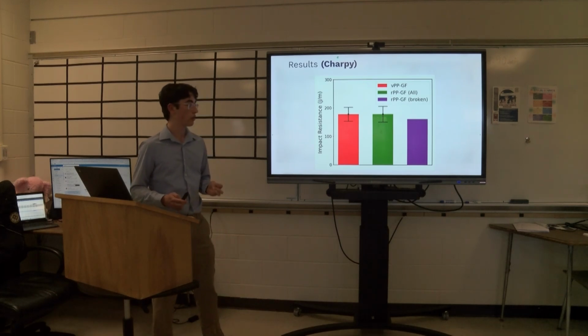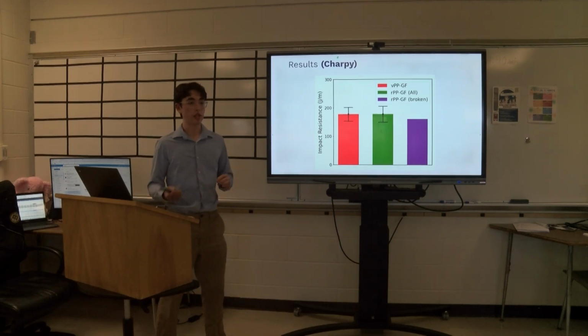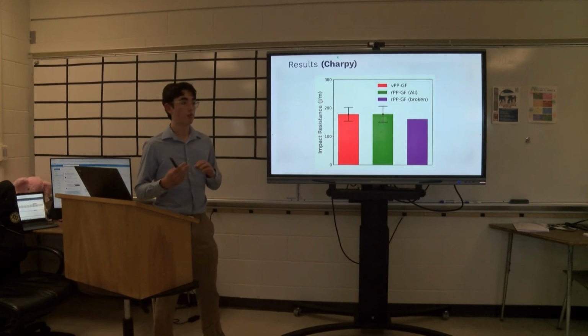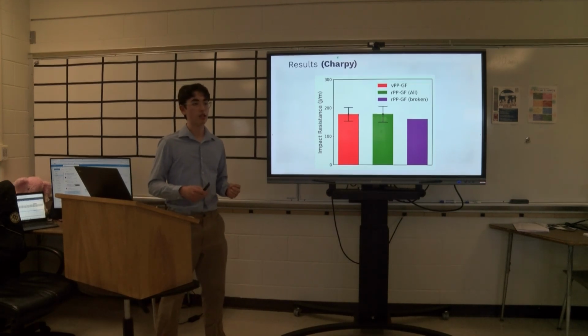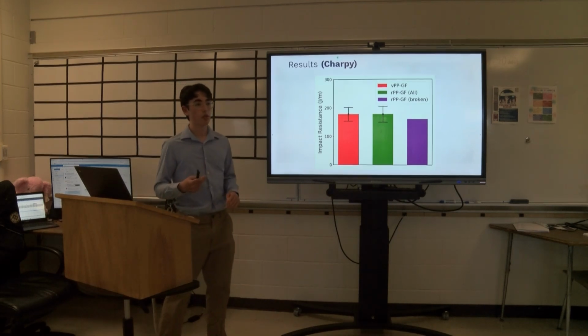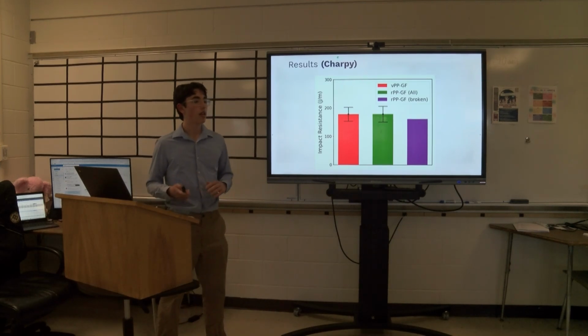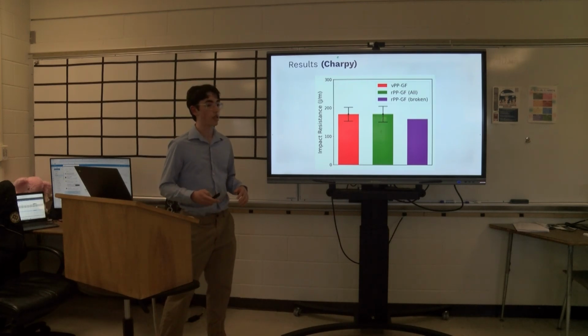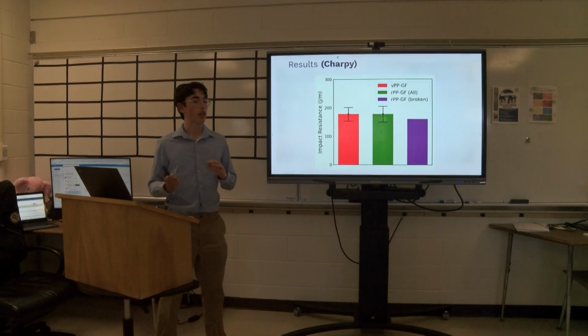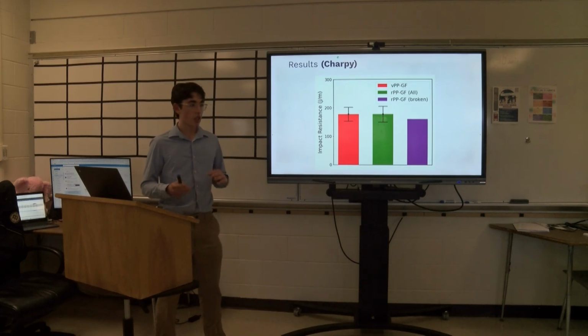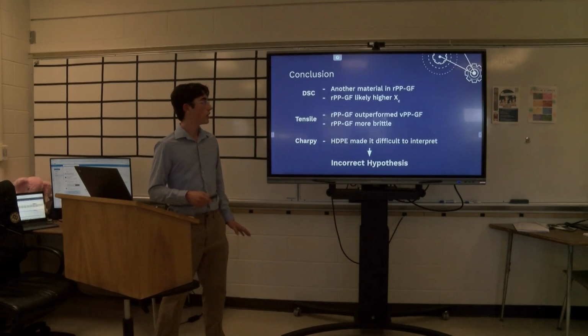Now, this is a little strange if we go back to earlier when we said that more crystalline material should have a lower impact strength. The reason for this is likely HDPE. One particular study by Awad et al. found that HDPE had as much as 4 times the impact resistance when compared with polypropylene. So it's likely this addition increased the impact strength of the composite. It's important to note, though, that this likely did not impact the tensile test as they have pretty similar tensile properties. All right, now let's move on to the conclusion.